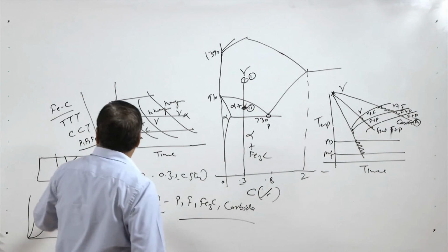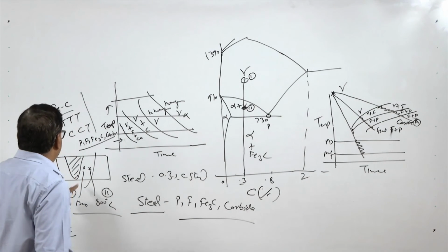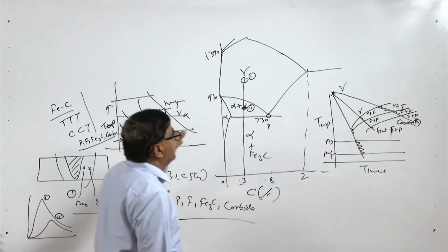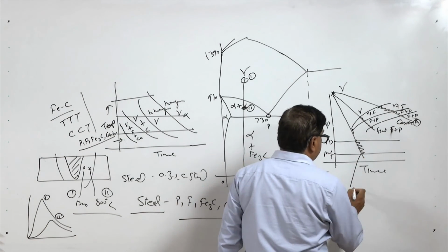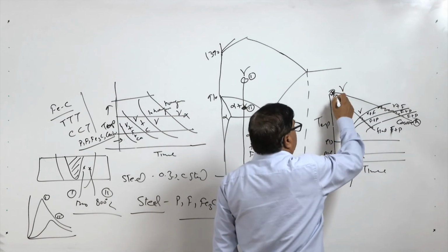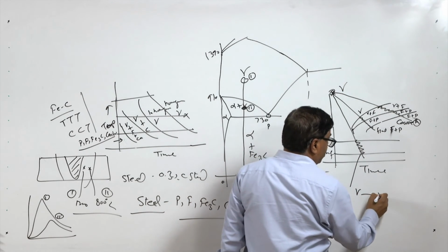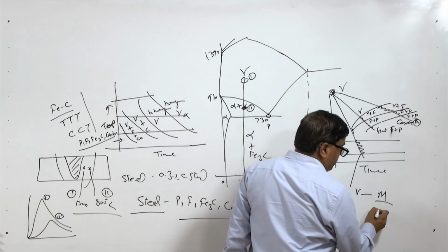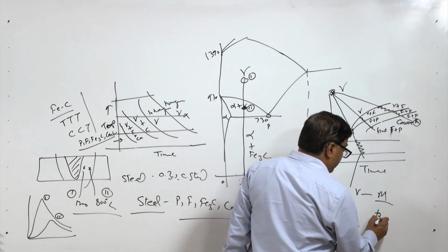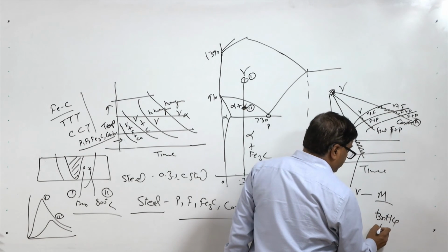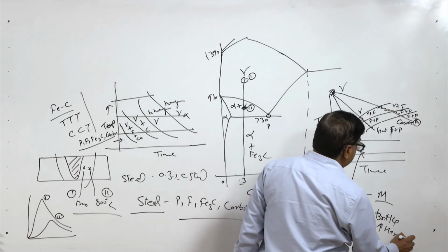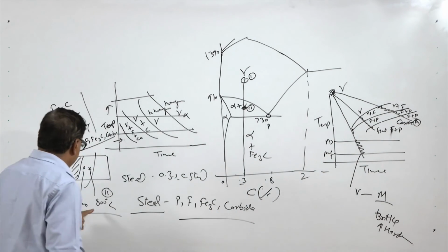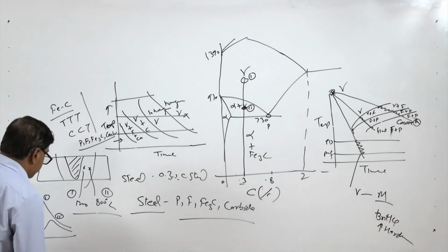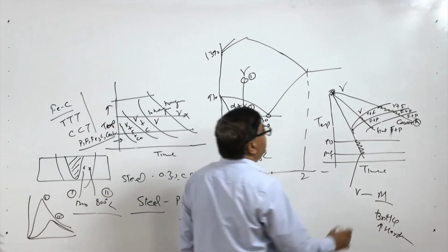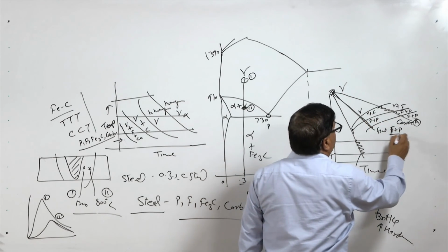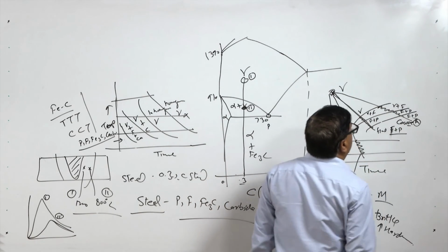So, as per the cooling rate, if point 1 is very close to the fusion boundary, it will be experiencing the higher cooling rate. It will be homogeneous austenite, and under the higher cooling rate conditions, austenite may transform into martensite. The martensitic transformation will be brittle, and it will lead to high hardness. On the other hand, point 2 is away from the fusion boundary and experiences the lower cooling rate. So, as per the cooling rate, it may have fine ferrite and pearlite, or it may have coarse ferrite and pearlite.